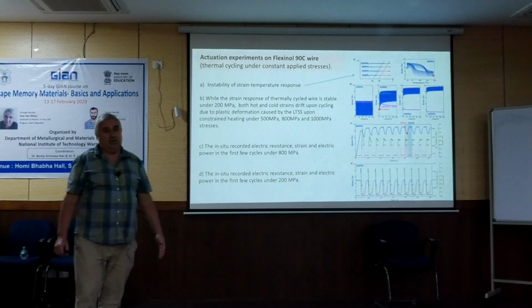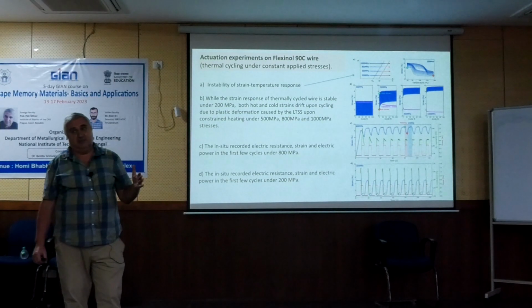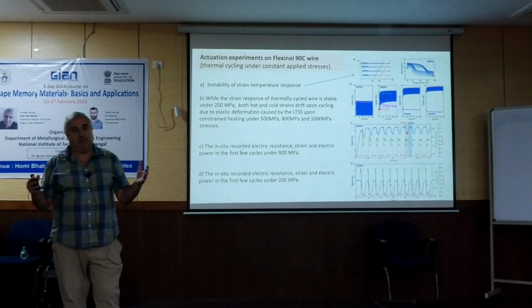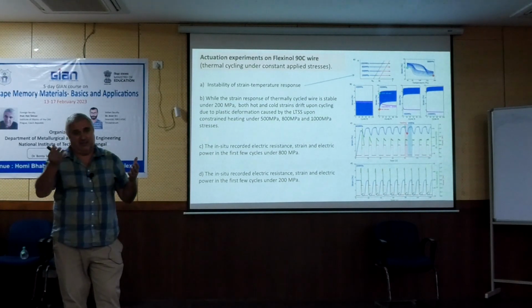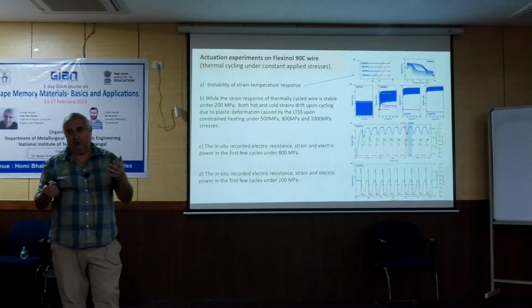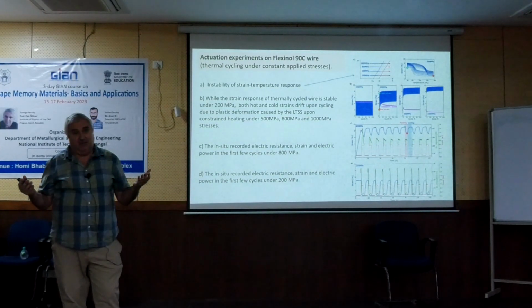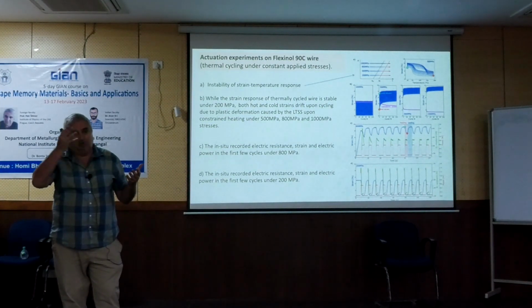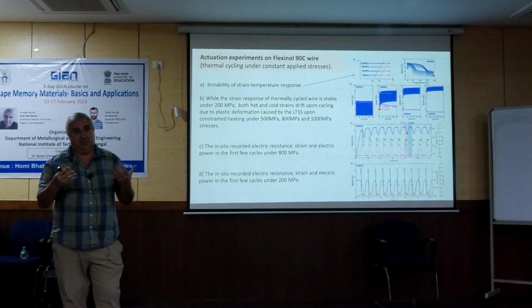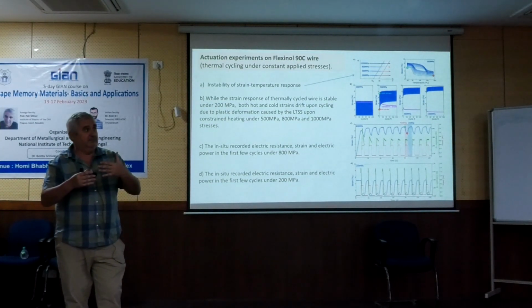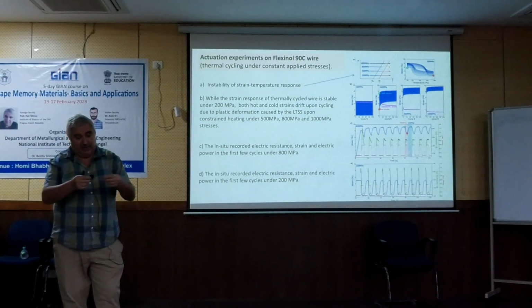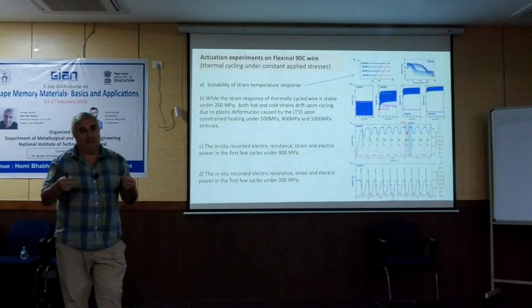Well, the elastocalorics is here like last 5 years. It looks like they have the concept that with loading a nitinol component and unloading, you take the heat out of the environment, you can make refrigerator. They are now already, it has a very powerful cooling coefficient, so lots of energy in one cycle, much more than during magnetocaloric cooling. But the problem is that the SMA element may fracture. So even though more energy is in tension, the element in tension will fracture.